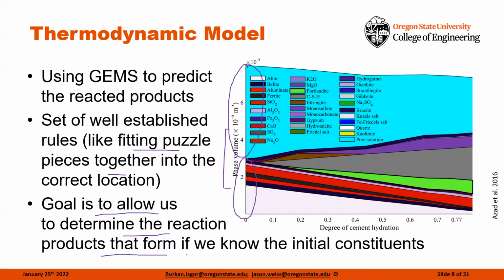And we're doing this based on the initial constituents that we have that are unique. So if you have a particular fly ash, a particular ponded ash, a particular specific type of material, we can bring that into the discussion and say, that's one of the initial puzzle pieces that we're dealing with. And over time, the cement and the SCMs are going to react with the water, and they're going to form these phases that we know, whether it's calcium silicate hydrate, shown here in gray, or whether it's calcium hydroxide, shown here in green. We can calculate how these are going to be produced over time.